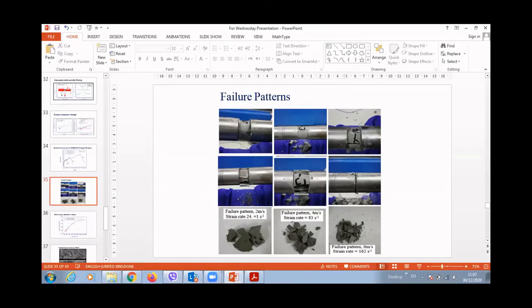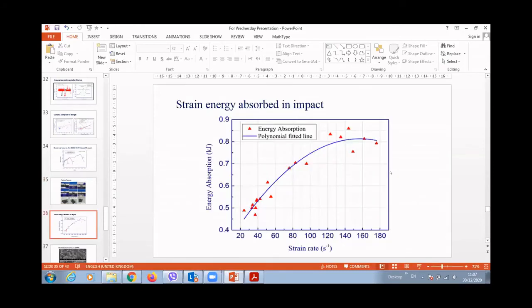And this gives us an idea to analyze the energy gained or absorbed by the samples during the impact. The representation shown is a polynomial fitting. The energy absorbed is increasing with the strain rate until it reaches the saturation stage, where the sample shows failure or starts cracking.